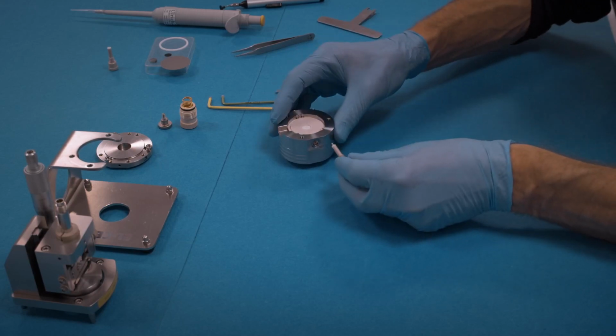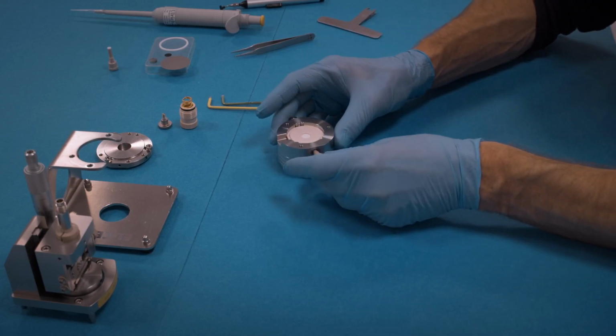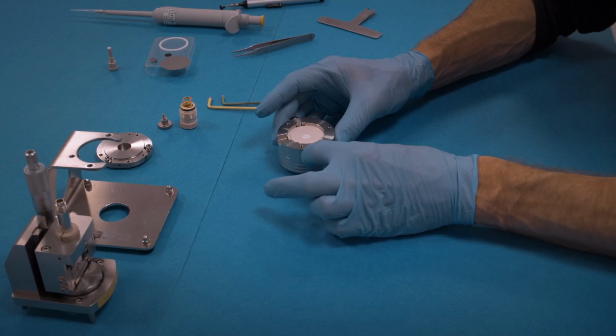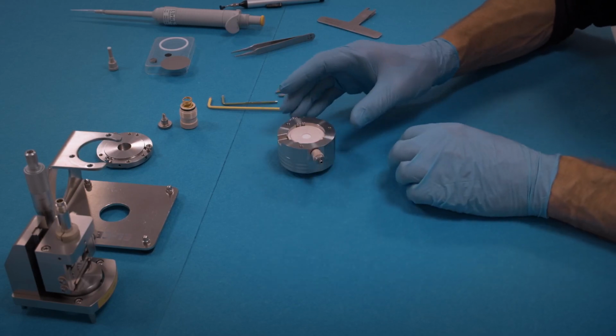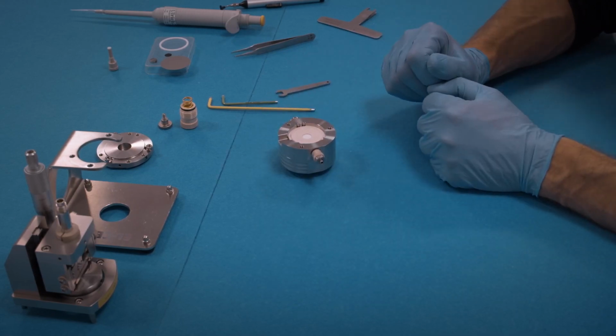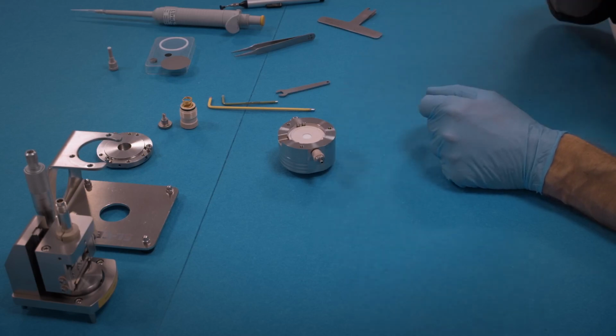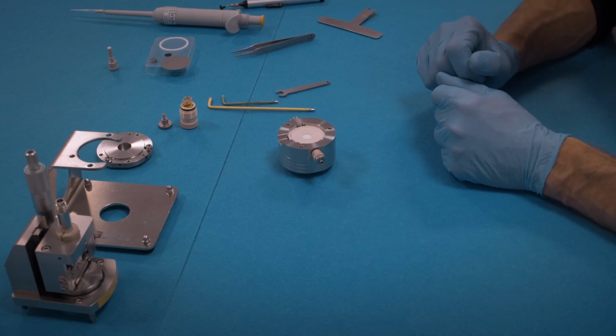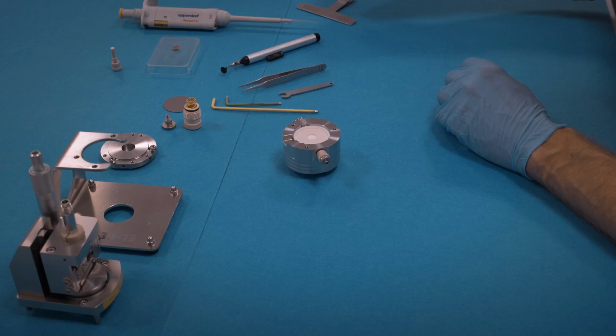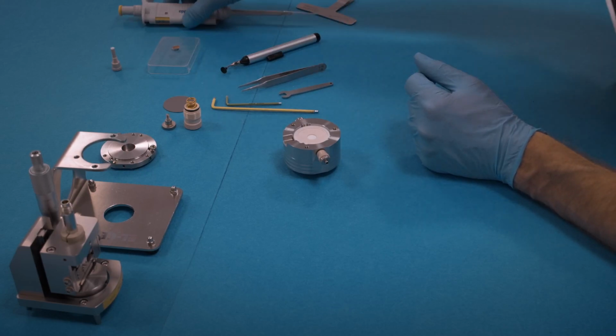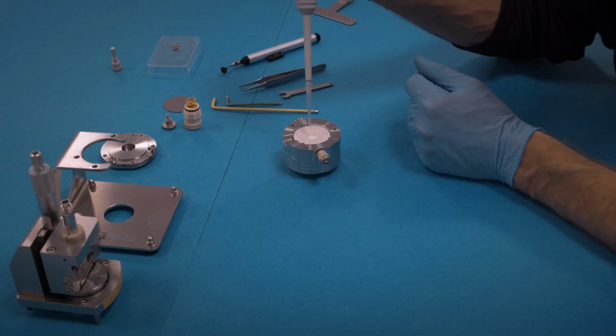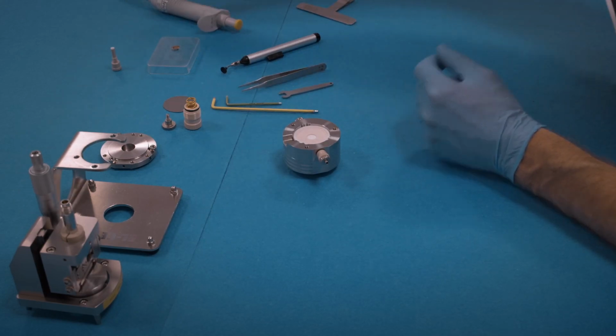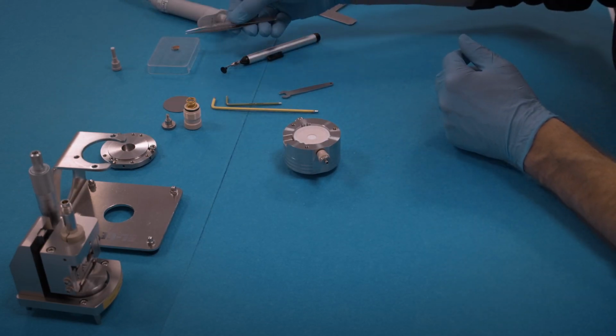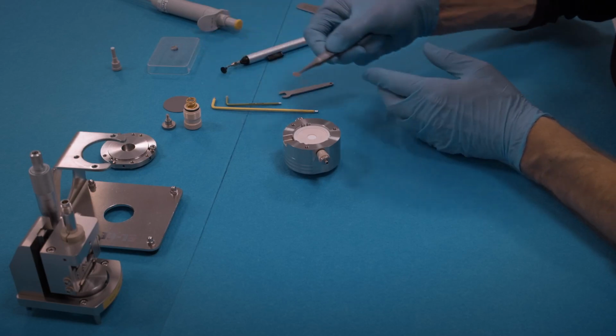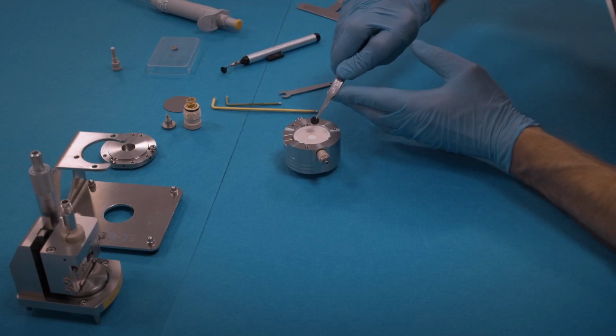Once the reference pin is filled with lithium, insert into the cell base, into the side opening, and only gently tighten at this point in time. We will later on tighten the reference. Then add electrolyte, about 350 microliters of electrolyte. Typically, you must see the electrolyte on top of the frit.